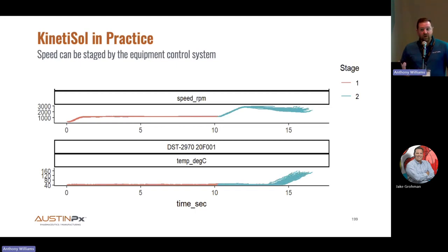And somebody said, well, what if the granules affect the process? Well, we just set the machine to run 2 stages and mix it for a little while. We know what mixers do, especially the type of mixer we have. It's just going to grind those particles away. And so we just mixed it at a low energy for a while to remove that granulation history that we added so that the material could get into the machine. And then the process did what you see normally: starting here, we ramp the RPM up to a speed that affects the viscoelastic property changes in the system that allows for the dissolution process to happen.